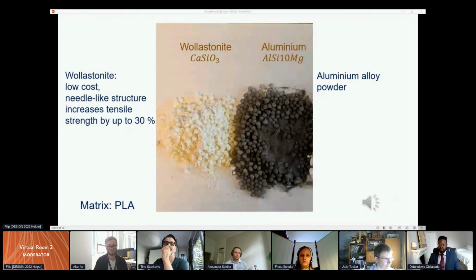The material selected for the matrix was PLA, which is well suited for additive manufacturing. It is biodegradable too. The additive materials used are wollastonite fiber and powder of aluminum. Wollastonite has potential in replacing more expensive reinforcing fillers such as glass fibers due to low cost and needle-like structure. Wollastonite increases tensile strength by up to 30%. Aluminum alloy powder with 10% of silicon was used as the second additive.